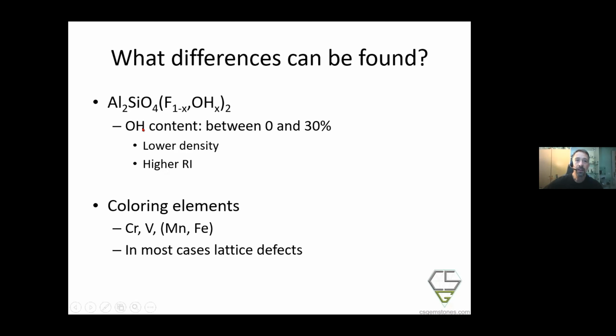The more hydroxyl we have, the lower the density becomes because the group is more bulky, it stretches the lattice, and therefore we have a higher volume. And what is interesting for gem cutting is we get a higher refractive index. So the more hydroxyl groups we have, the higher the refractive index is, the better the cutting properties are for a gemstone. The coloring elements in topaz are not that many because we have chromium, vanadium, which are known to